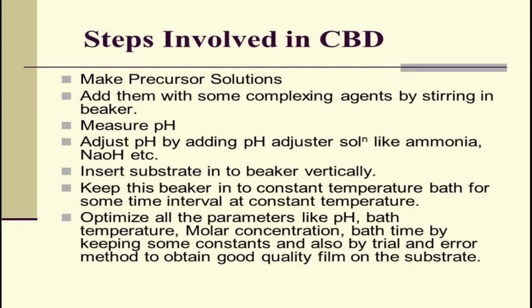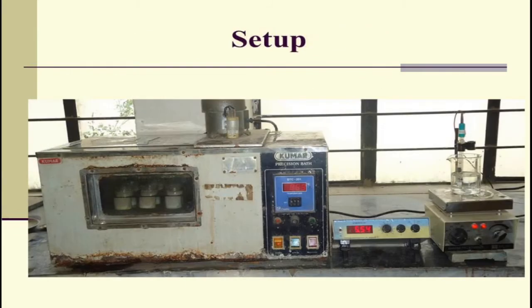Steps involved in CBD: make precursor solutions, add them with some complexing agent by stirring in a beaker, measure pH, and adjust pH by adding a pH adjuster solution like ammonia or NaOH, etc. Insert the substrate into the beaker vertically. Keep this beaker in a constant temperature bath for some time interval at constant temperature. Optimize all parameters like pH, bath temperature, molar concentration, and bath time by keeping some constant and also by trial and error method to obtain a good quality film on the substrate. This is my setup in my laboratory.